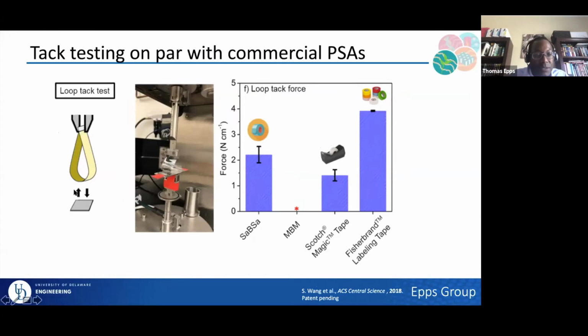So just a loop tack test where we take our sample, basically put it down on a slide or a piece of stainless steel, and then pull it off and measure the peel force. And you can see the same sort of thing. Now, one of the nice things is that we can actually add additives such as tackifiers, for example, to move this up in particular and match things like Fisher brand labeling tape, or even adjust things to Scotch Magic tape, for example. We asked 3M, for example, what their exact additives were. They, of course, wouldn't tell us, but we were able to make some good guesses and we're able to get materials that fall right in line with that.